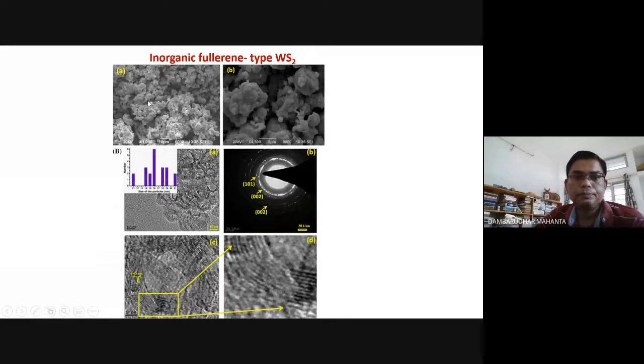So here, first the scanning electron microscope shows cauliflower-like structures, but under TEM, we found that these are actually cage-like structures having hollow cages inside. And the last part is the high resolution TEM picture. You can see that you have lattice fringes on the outer part, whereas the inner part is empty.